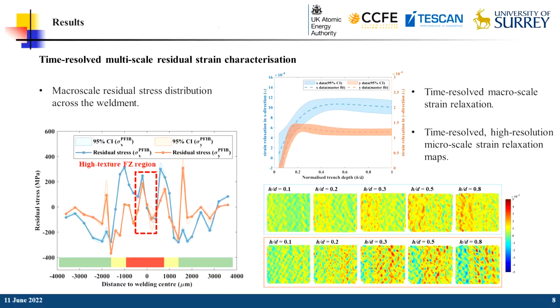From the strain relaxation mapped at the right bottom, we can see that the residual strain relieves gradually during the milling processes, and the localized accumulation of the micron-scale strain relaxation can be an indicator of the crack initiation and the failure. Looking at the color bar, the microscale strain could be significantly larger compared to the macroscale residual strain.